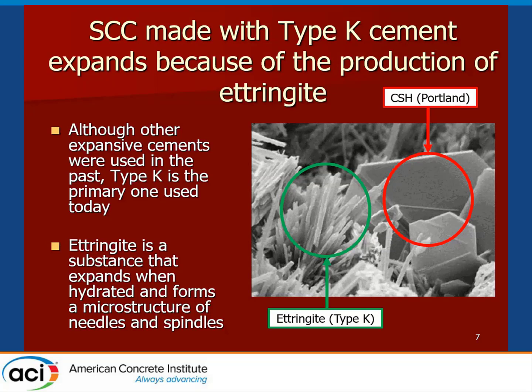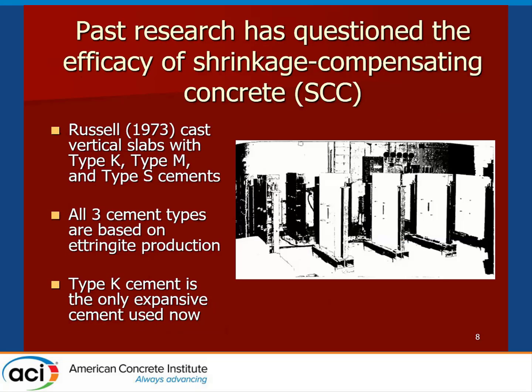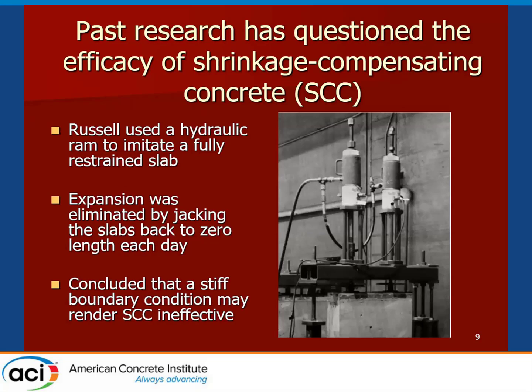Type K cementitious shrinkage compensating admixtures are the most commonplace today. Some past research has looked at whether external mechanical restraint will reduce the efficacy of shrinkage comp. Russell in 1973 looked at three different types of shrinkage comp, used a hydraulic ram to imitate a fully restrained slab condition, and concluded that stiff boundary conditions may potentially reduce the efficacy of shrinkage comp.